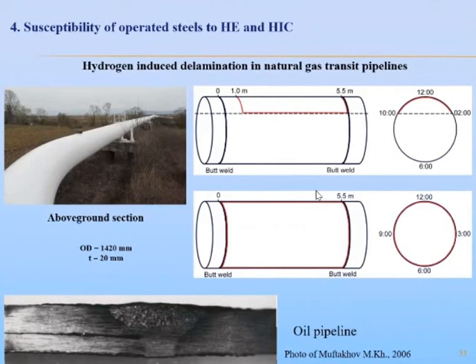It means that they were subjected to climatic temperature changes, and therefore there were conditions for moisture condensation on the pipe internal surface. And as with earlier, condensed water serves as a source of hydrogenation due to corrosion, and thus hydrogenation of pipe steel from internal surface is possible. And hydrogen diffusing from the internal surface in the direction to external surface can be trapped in different defects and recombine into molecular state.